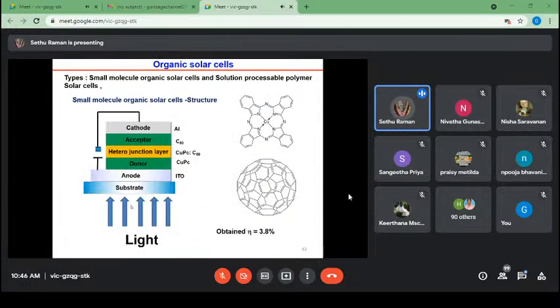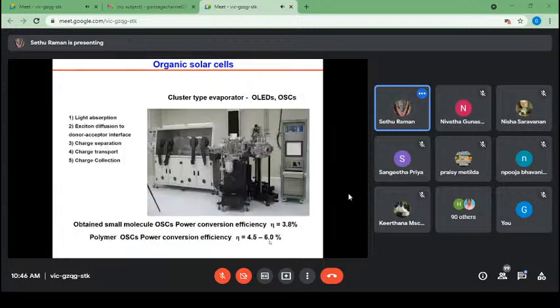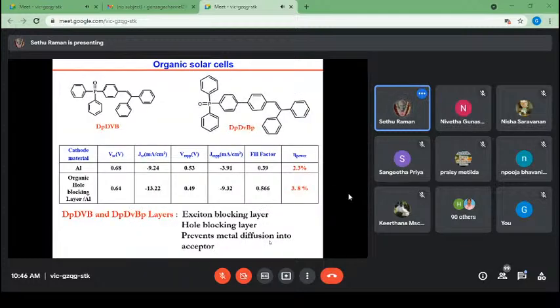This is some work I have done, a small molecule based organic solar cell using evaporation technique. C60 is the acceptor, and the planar heterojunction layer solar cells were prepared with copper phthalocyanine as the donor. I prepared all the layers by thermal evaporation technique and achieved a power conversion efficiency of about 3.8 percent during my stay in Korea and Japan. These are some instruments used for the deposition of organic light emitting diodes and organic solar cells, with some blocking layers used to enhance the power conversion efficiency.